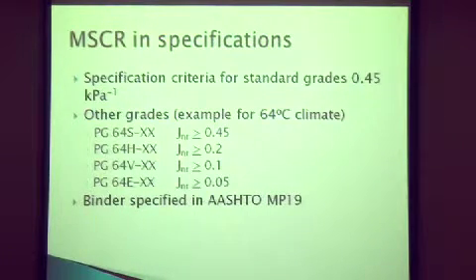So it's more in line with the original Superpave and SHRP specifications, that you're evaluating a property at the temperature that your road is. This is much more consistent with Superpave rather than the ad hoc grade bumping that was adopted in the mid-1990s. So this is a slightly different approach. AASHTO specifications for these are all standard, they're all published, and you can get hold of these fairly easily.